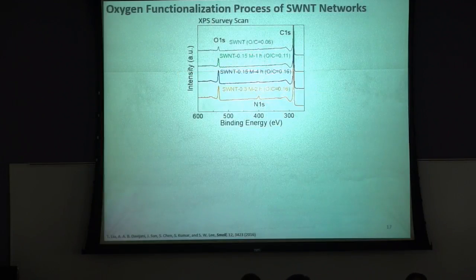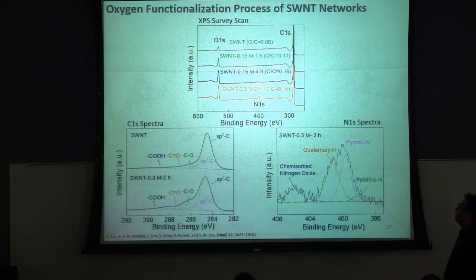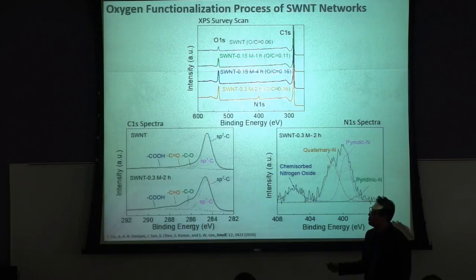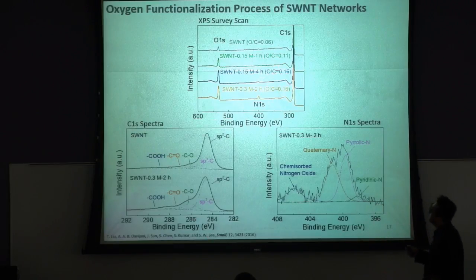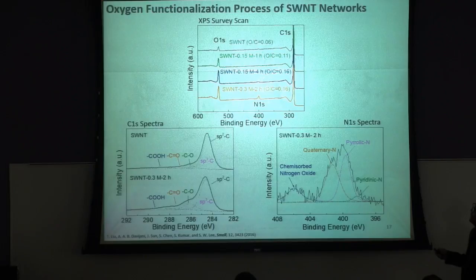Then, let's look at the surface chemistry. The pristine single-walled carbon nanotubes have an oxygen to carbon ratio of around 0.06. We can increase this ratio by increasing the oxidation time or the concentration of nitric acid. Then we can see incorporation of various oxygen functional groups, including carbonyl groups. And interestingly, if we increase the concentration of nitric acid, let's say to 0.3 molar, we can see nitrogen doping, the incorporation of various nitrogen functional groups in the carbon nanotubes.